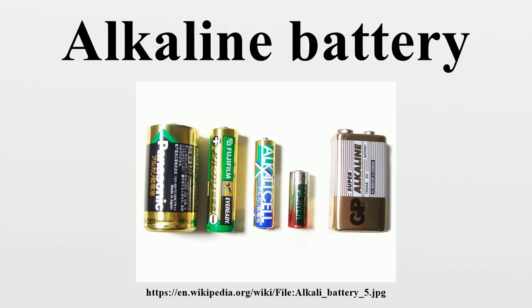contribute to containment failure. Once a leak has formed due to corrosion of the outer steel shell, potassium hydroxide absorbs carbon dioxide from the air to form a feathery crystalline structure of potassium carbonate that grows and spreads out from the battery over time, following along metal electrodes to circuit boards where it commences oxidation of copper tracks and other components, leading to permanent circuitry damage. The leaking crystalline growths can also emerge from seams around battery covers to form a furry coating outside the device that corrodes any objects in contact with the leaking device.